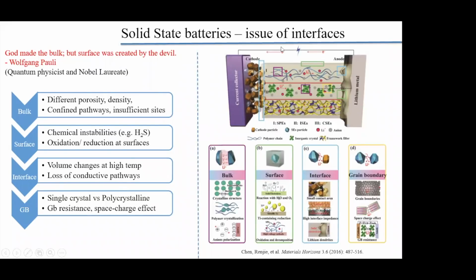So to summarize the issue of interfaces, let's put those two things together. This is from the same paper. We have bulk interfaces. At the bulk interfaces, you need to solve the problem of porosity. Different materials have different density, and you need to make sure of a seamless mixture. You need to make sure there are no confined pathways. For example, lithium should have sufficient sites to go from one site to the other. If it is all concentrated in one point or another, it can lead to imbalance, and that could be a failure point. It has to move uniformly back and forth, and the whole interface has to have the right kind of porosity and density of materials. Pathways should exist along the whole surface. So that's at the bulk level.